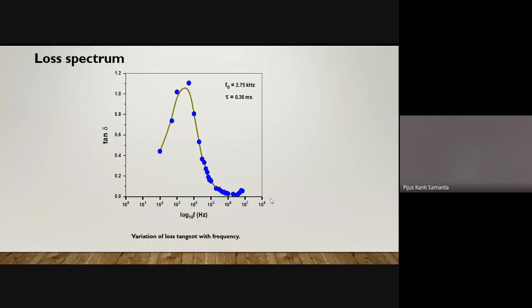To study the relaxation phenomena, we show here the loss tangent spectrum as a function of frequency, which shows an initial increase of the loss tangent to critical values up to 2.75 kilohertz, and it gradually decreases for higher frequencies. Now, this is because, as we know from the theory of dielectric polarization, on application of an alternating electric field in a dielectric sample, the dipoles tend to oscillate with the frequency of the applied field. But beyond a certain frequency, the dipoles may no longer be able to follow the oscillations of the electric field, and the oscillations of the dipoles become out of phase, leading to the dissipation of energy. So this is how the energy dissipation occurs.